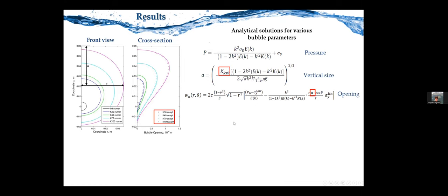So what you can see, also from these new simulations, and also from that fracture toughness, this parameter, that I will repeat again, the parameter that defines the strength of cohesion between the grains in muds. And this cohesion can be of different kinds, okay? Fracture toughness significantly affects the mature bubble shape and size. For instance, this is a vertical semi-height, and you see here this fracture toughness, and this is the opening, which is a function of this semi-height.